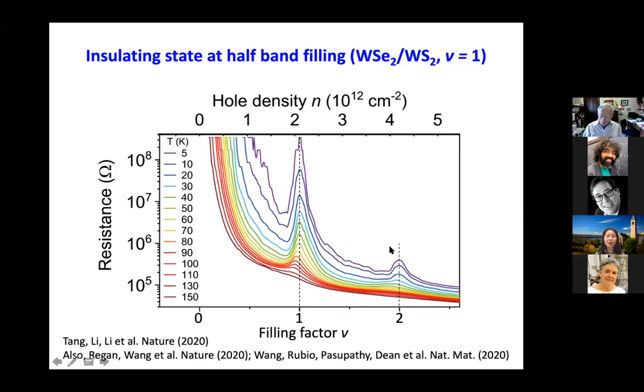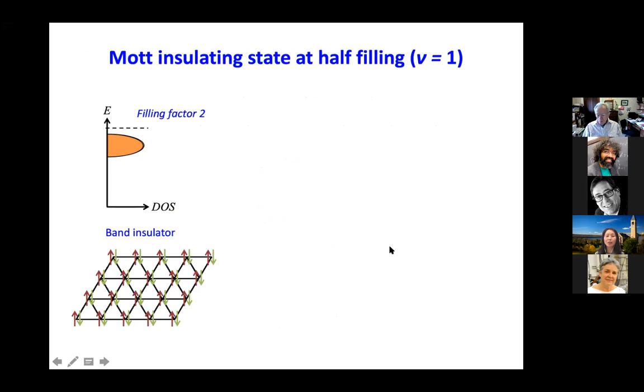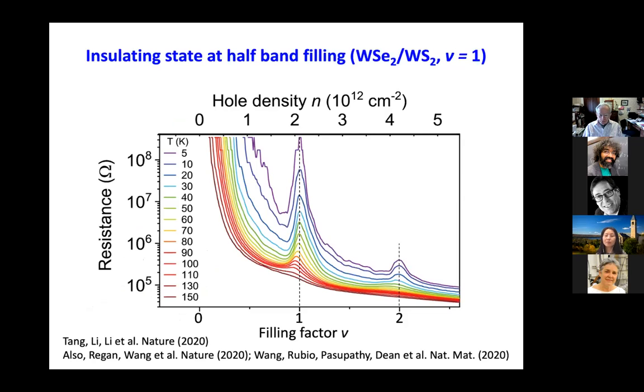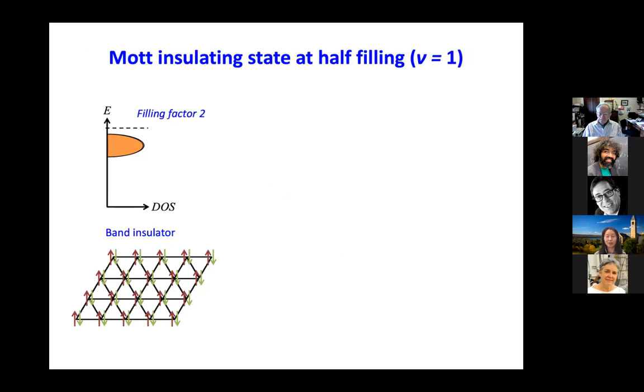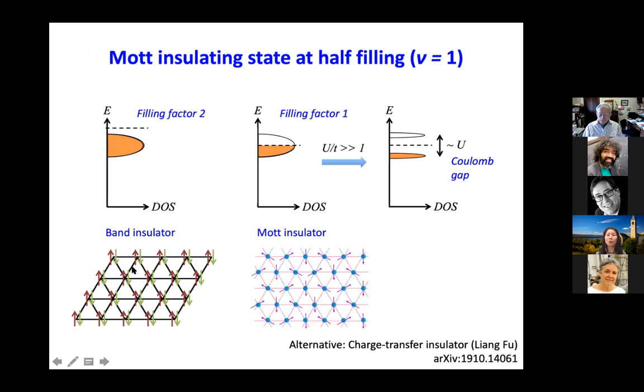The peak at 2 particles per site is something we know very well, because now we have completely filled bands, so it's a band insulator. The resistance will increase when you cool the sample down. So this is just a regular insulator. But the insulating behavior at half filling, 1 particle per site, has a very different nature. This is driven by interaction. When the Coulomb interaction is strong, it can break this band into 2 by introducing this Coulomb gap.